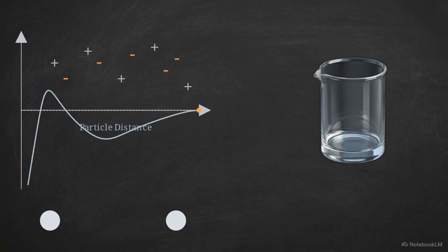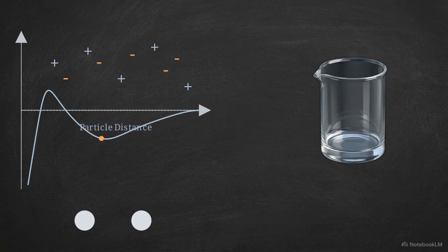By adding electrolytes, we suppress the zeta potential and shrink the repulsive energy barrier. This shifts the entire DLVO plot downward, creating a deep enough secondary minimum to trap the approaching particles before they reach the primary minimum. Here, they form a loose, bulky structure called a floc. The particles sediment, but because they are loosely bonded, they easily resuspend upon agitation.